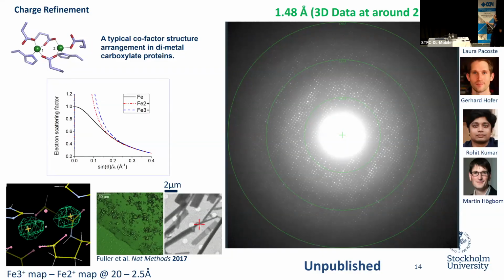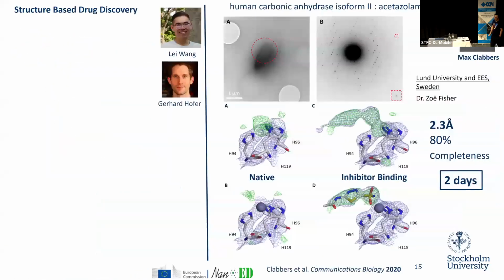And thirdly, as you can see here, we have severe beam damage. So if we just take one diffraction shot from the crystal, we can get 1.5 angstrom resolution data. But if we take 3D data collection, we cannot get this resolution simply because of beam damage. So we are now trying to design new ways, maybe doing serial electron diffraction, or doing small wedge data collection, or doing a helical scan on these crystals. Right.